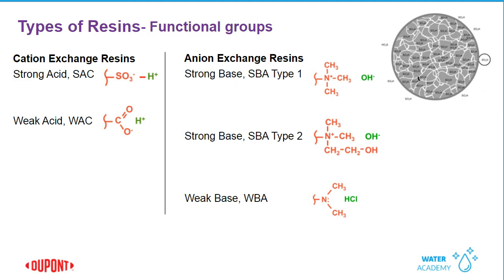The strong base type 2, which is also a quaternary ammonium ion, has a bulkier side chain than the type 1 anion. And this reduces that positive charge on the nitrogen, making this resin easier to regenerate than the type 1. However, it also makes it hang on to silica less tightly than the type 1. And so for this reason, that's why the type 1 is preferred.